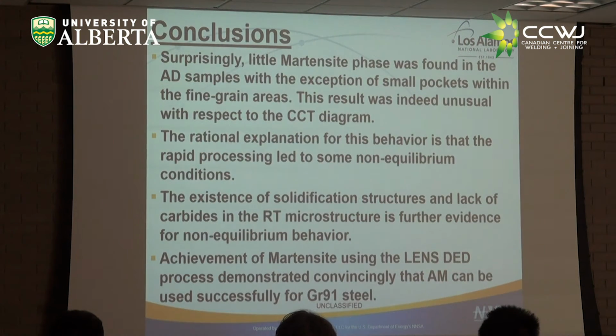So I think with that, I'm going to stop and slow down here. Conclusions. We've gone through this before. Surprisingly, we found little martensite in the as deposited samples, with the exception of the speckled region. This was indeed unusual compared with what we expected according to the continuous cooling transformation diagram. Something about the rapid cooling rate leads to yet to be determined non-equilibrium conditions, which give us this interesting microstructure.